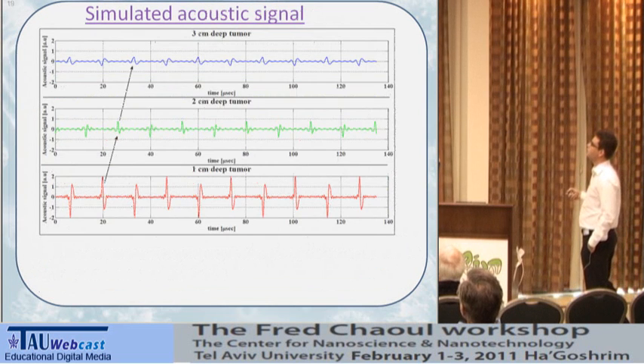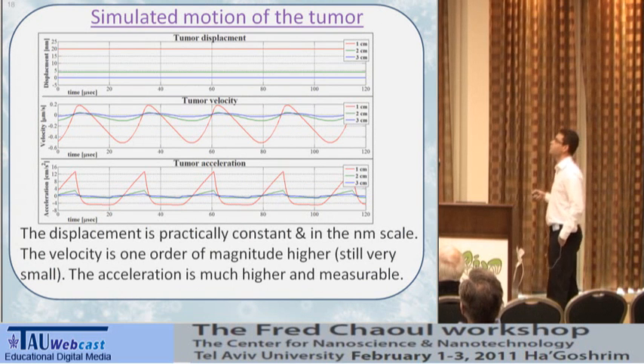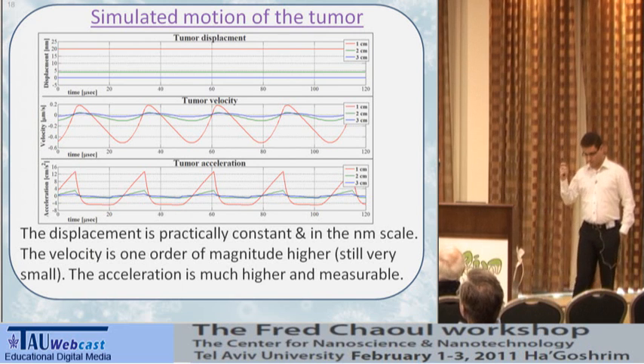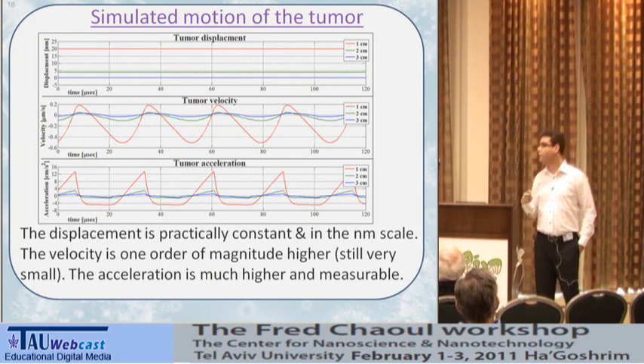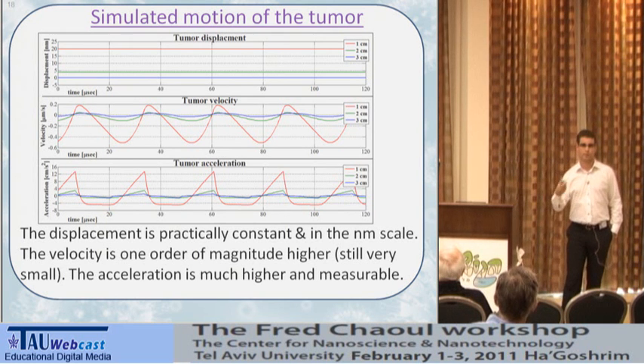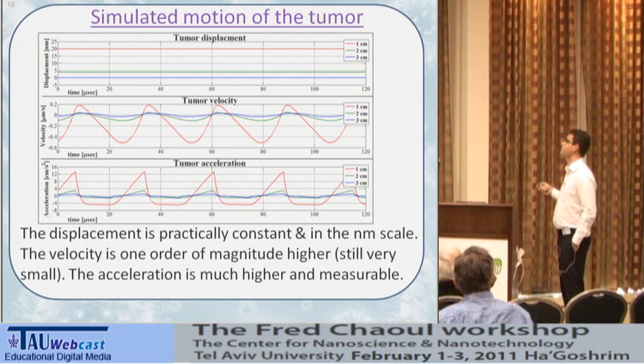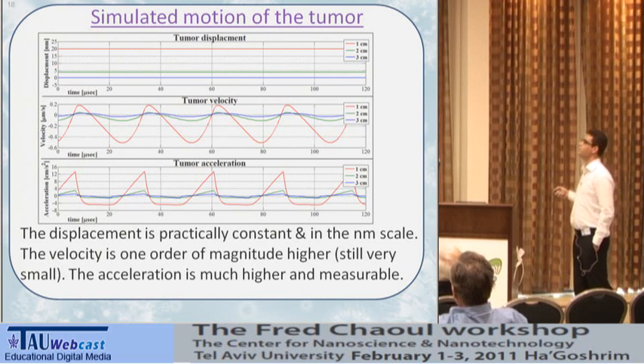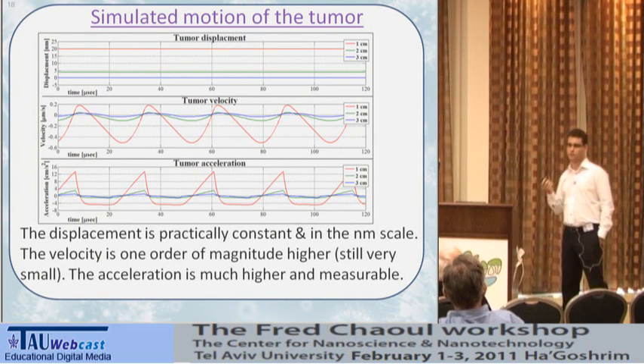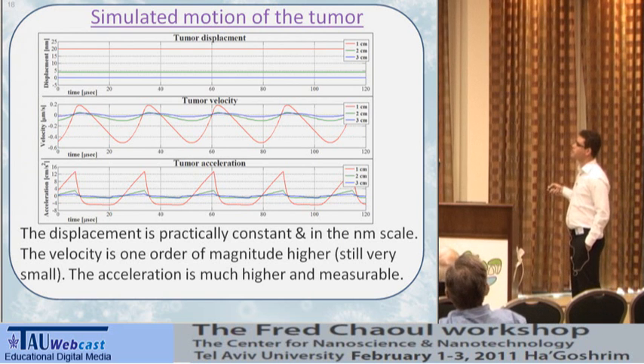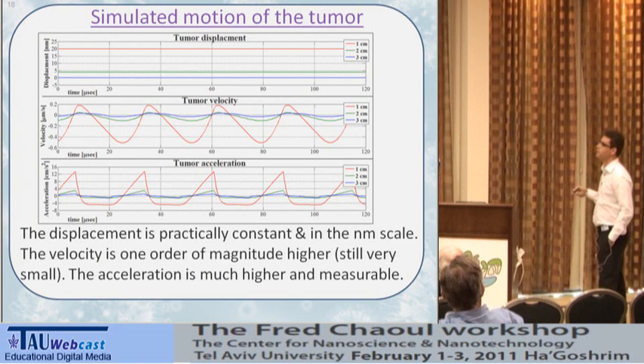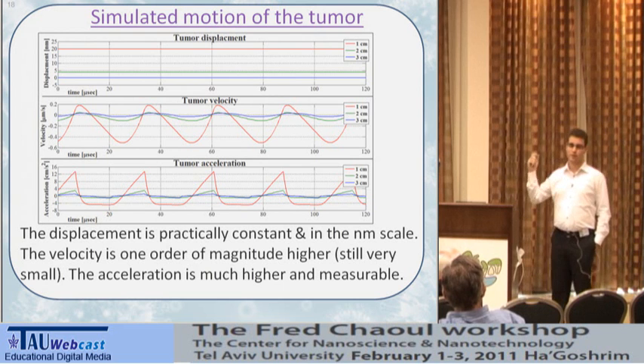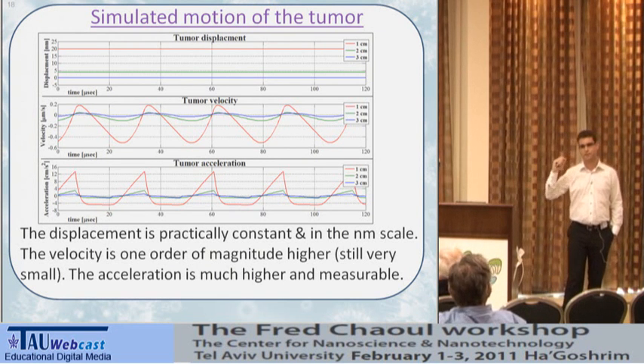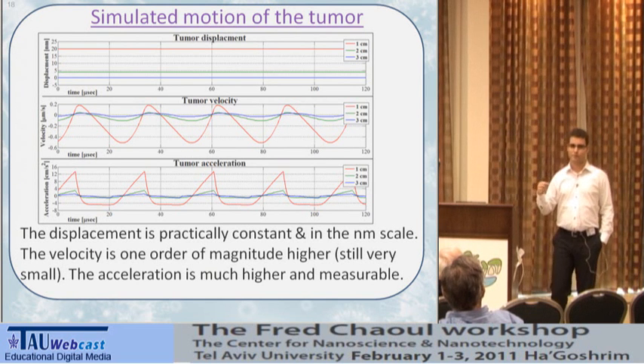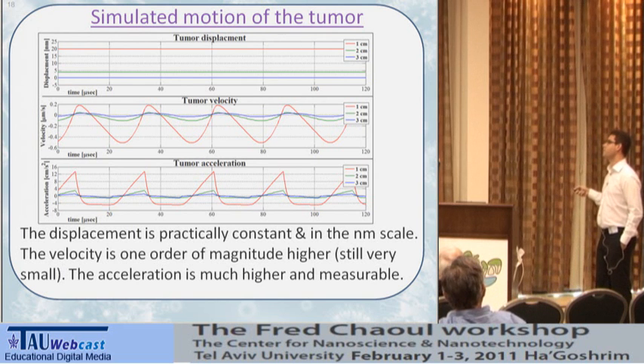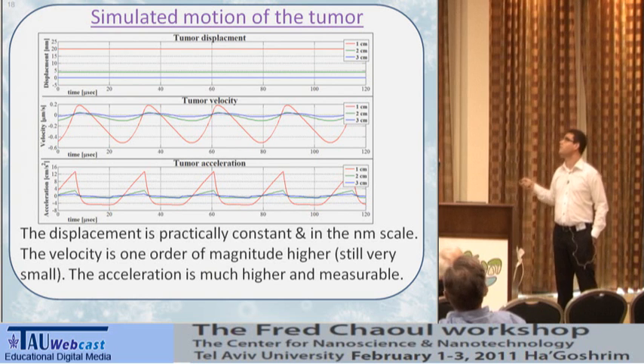Also, we look at the velocity. We see the velocity is on the order of a few micrometers per second. This is also important. Why? At some point, we thought about detecting the movement of these nanoparticles with Doppler ultrasound. And the Doppler shift is, of course, related to the velocity. We see the velocity is very small, so it will be hard to get a good Doppler shift. But we see the acceleration is actually okay. It's a few centimeters per second squared, which is measurable. And as we saw earlier, the acoustic dipole strength is directly proportional to the acceleration. So we rather measure something which is proportional to the acceleration and not the velocity or displacement, of course.